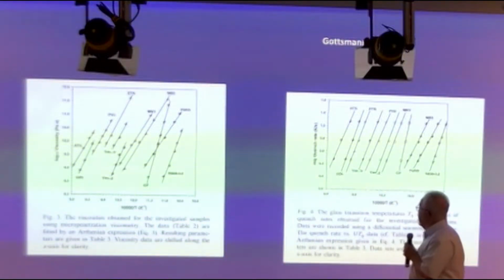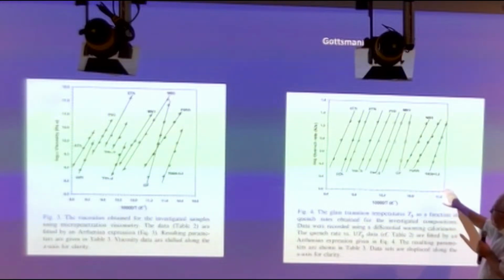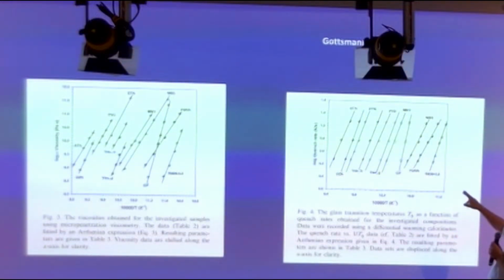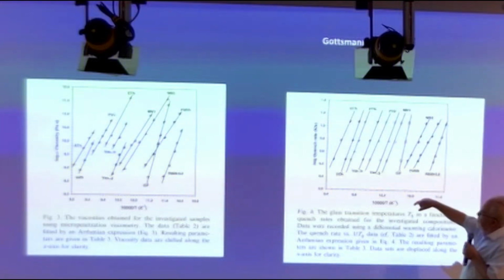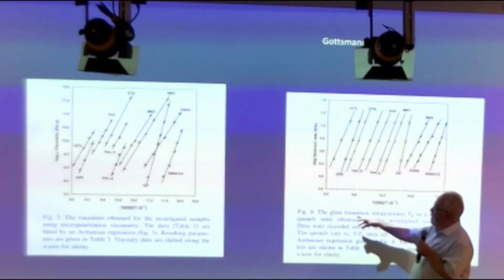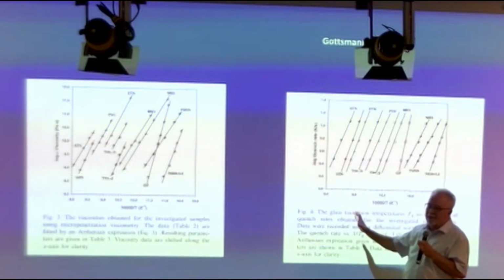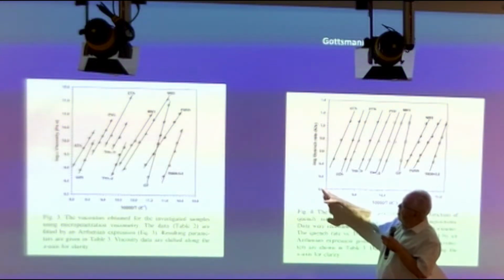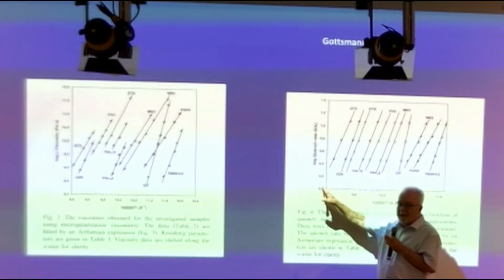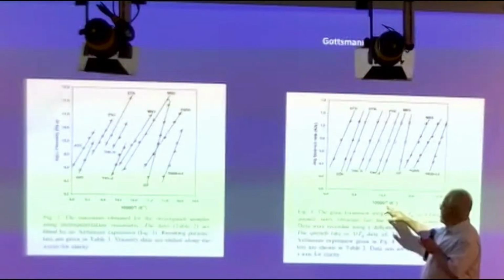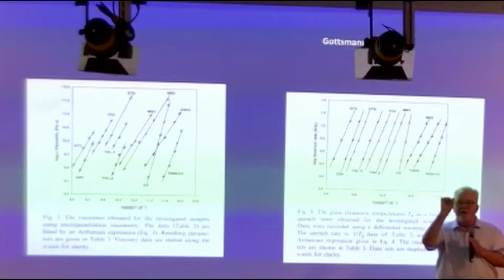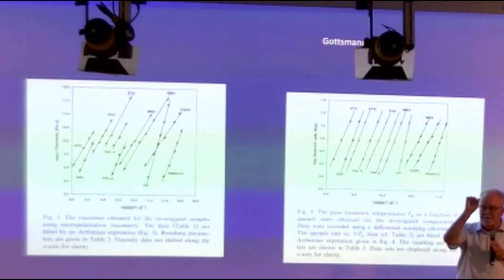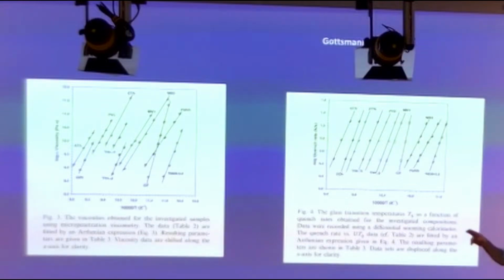And here you have a plot of a different kind of data for the same samples. You can see these names here, but what are we plotting here? You've got to stare at it for a minute and listen to what I say. We're plotting the log of the cooling rate or the quench rate versus a temperature, but what temperature? It's the temperature where that peak occurs. And the observation that you have to make from left and right is the slope is the same.